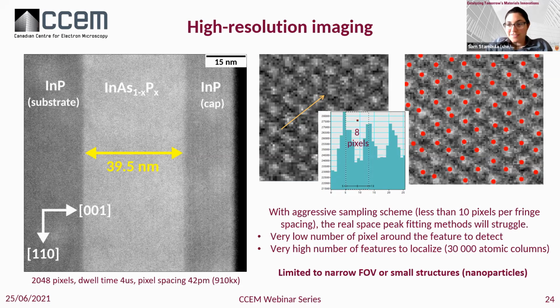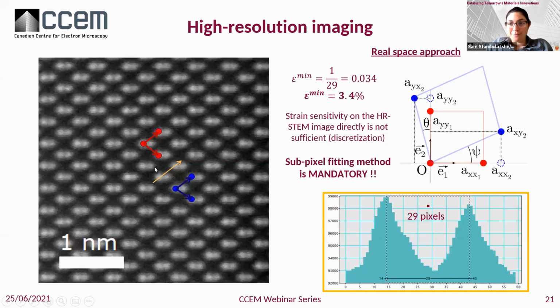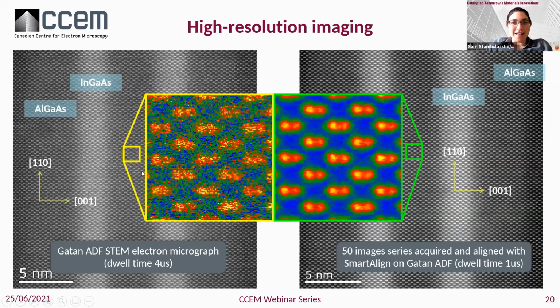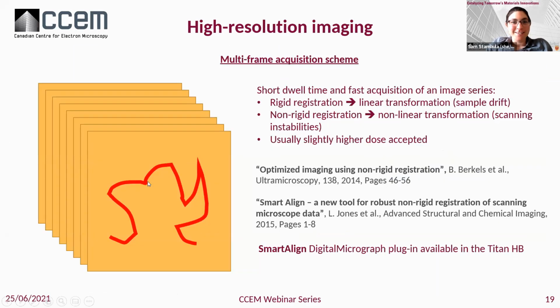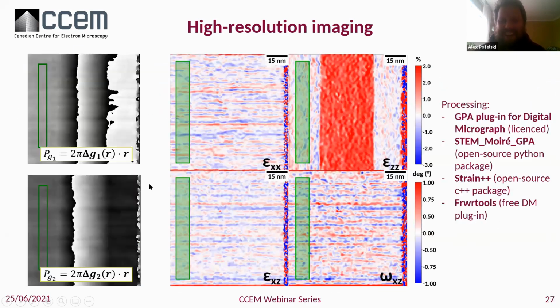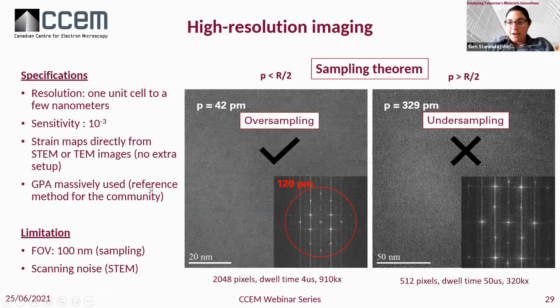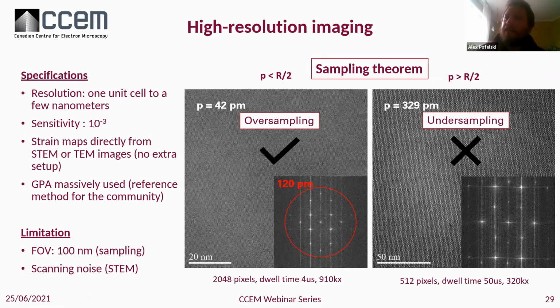Okay, great. And just one note: both Alex and I were sent a note from Colin Ophus, which is exciting since I think Alex referenced one of his papers. Oh yeah, that's great work. He wanted to note, in terms of the drift correction, that he would strongly recommend rotating the scan direction between 0 and 90 degrees when collecting data for strain mapping. SmartAlign will work even better with the rotated images. Yes, to not have any bias regarding the direction of the crystal that you use.